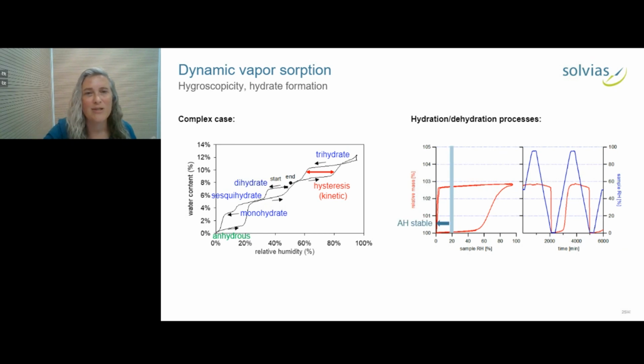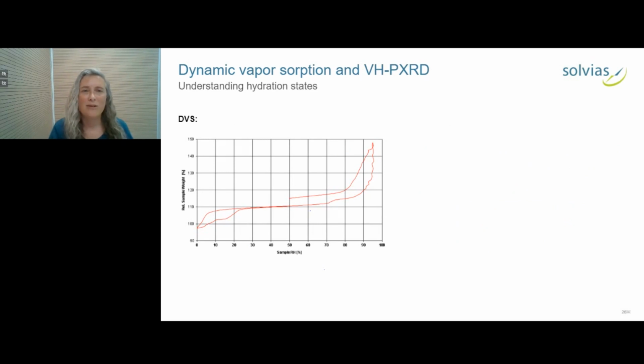So below 17% relative humidity, the anhydrous form was stable, and above, the monohydrate was stable. And so then it was very clear in this case that the monohydrate would be the form developed. And we can also use X-ray diffractogram, this time in situ varying the humidity, to understand dynamic vapor sorption. And here you see again a case with several steps.